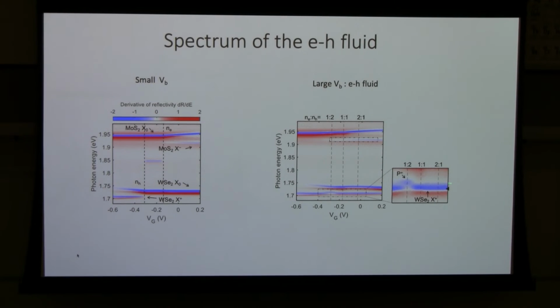So you can see this original intralayer trion signal disappears, and a new feature appears. If we zoom in on the corresponding region for the electron layer, or if you squint your eyes, you might say there might be something happening at 2 to 1 where the spectrum becomes a little bit broader, but it's very hard to see. The reason is initially this peak is very broad, so it makes the small change harder to detect. As a result, we'll just focus on the hole-doped region where the hole density is twice the electron density and look at this spectral feature more carefully.